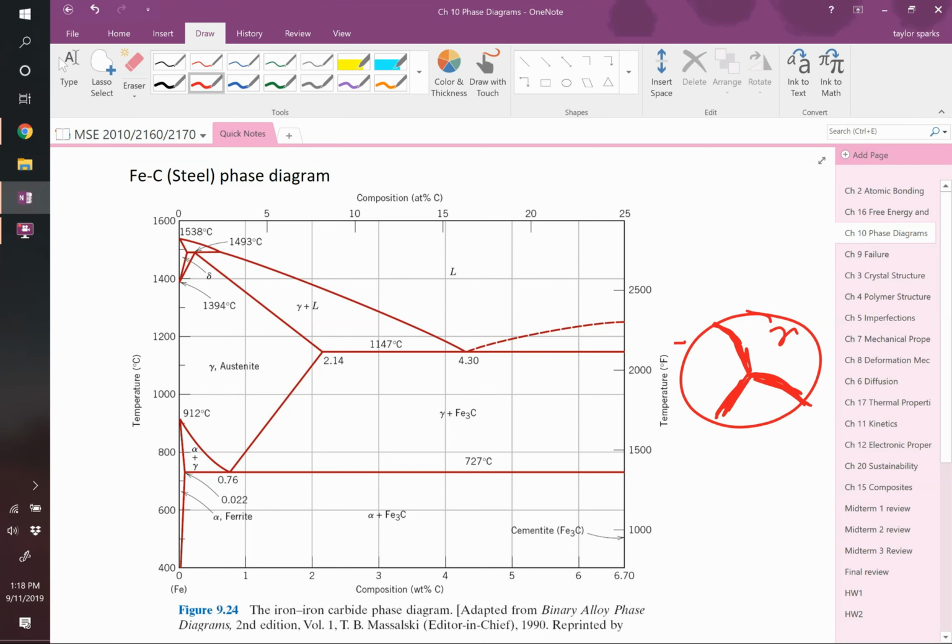So this can only happen at high temperatures, right? Atoms have to be able to diffuse to the grain boundary. And we're talking about pretty high temperatures, typically in the 900 to 1,000 range. That's getting pretty hot. So if you do it slowly enough, things will form along these grain boundaries. What happens if you do this really quick or it happens at low temperature? How would the structure look different? Yeah, you'd have speckles, basically. You would have your grain boundaries from before, and you'd have speckles of your cementite phase. If this happened at low temperatures or really quickly, you'd expect that. But thermodynamically, they'd like to start coalescing, and that typically means along grain boundaries.